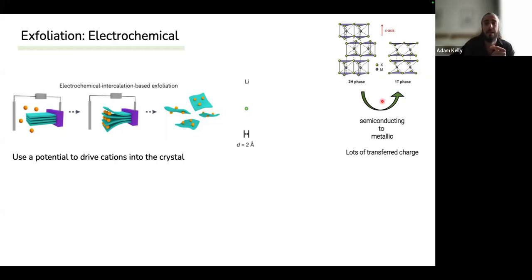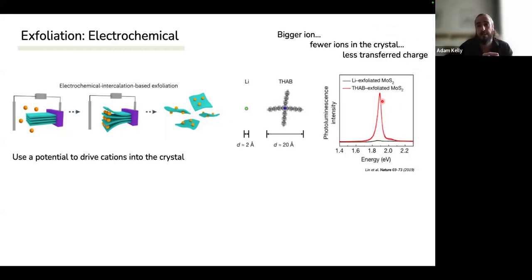You want a semiconductor. So these guys, Lin et al. in Nature in 2019, decided to use a larger ion. They used one of these tetraalkyl ammonium ions, which are quite bulky. They have a diameter which is about 10 times larger, which means there are fewer ions intercalated into the crystal, which means there's less charge transfer.